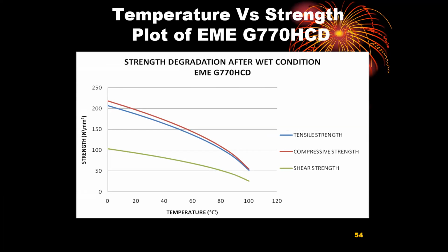Coming to the other encapsulant materials that we also considered, I'm sure a few other encapsulant materials were also considered, but I'm just giving you a hint of how different encapsulant materials play a big role with respect to their wet TG, other things being more or less equal. So the wet TG plays a big role in the choice of the encapsulant and the process itself, compared to the MOT, or the maximum operating temperature, and the lowest wet TG, or the glass transition temperature. As it plays a big role, we have to be very careful about choosing encapsulants.